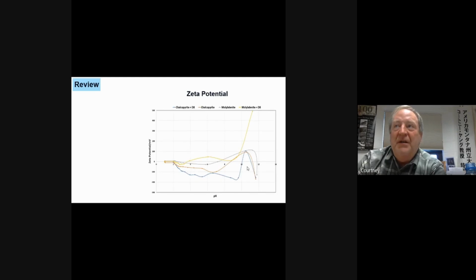So let's take a look at zeta potential with Orfom D8. Here's the chalcopyrite without Orfom D8. I should start there, and that's this plot that you see here. If you go above pH 10, then you start to get charge reversal. I'm mostly interested in here from pH 6 to 10, give or take.